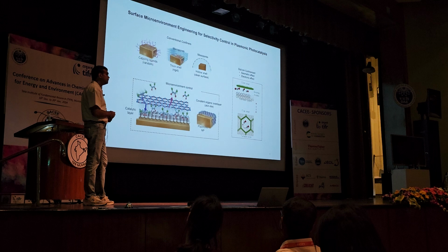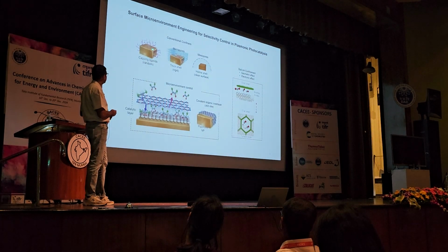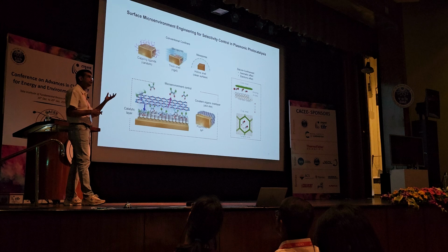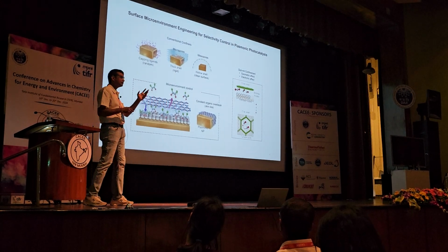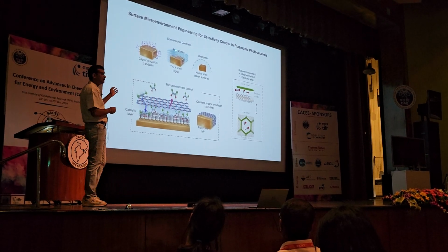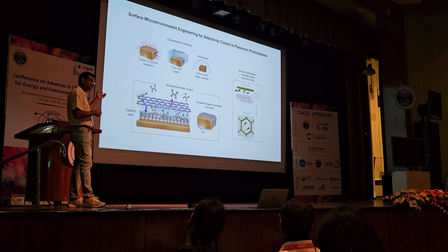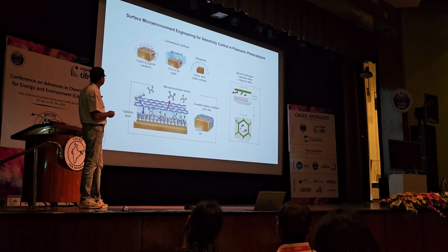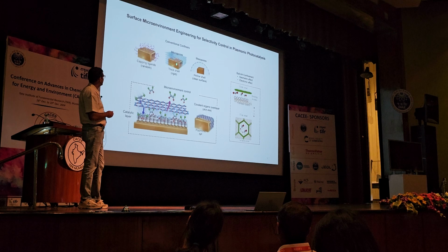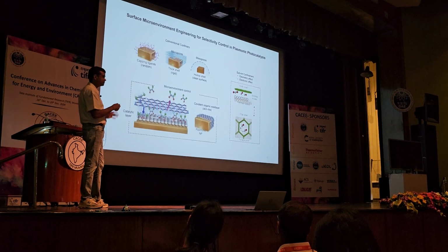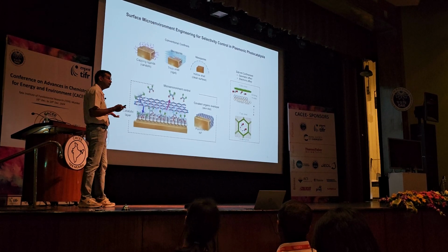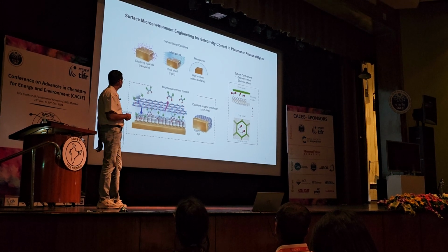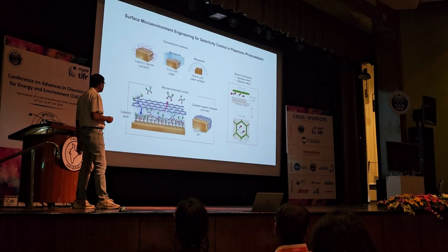There are several ways. You can modify nanoparticles with certain ligands, which may have some function. But as you know, ligands are usually conformationally flexible, and they can orient themselves in unpredictable ways, so that may poison the catalyst sometimes. Another way, you can encapsulate plasmonic nanocrystals inside thick, porous shells like MOFs, zeolites, etc. But they have molecularly restricted pore size, so the diffusion may be slower.